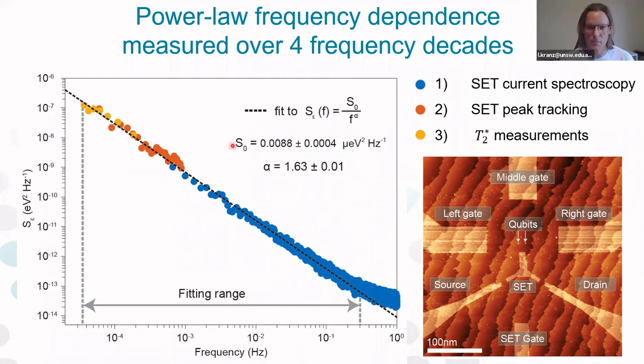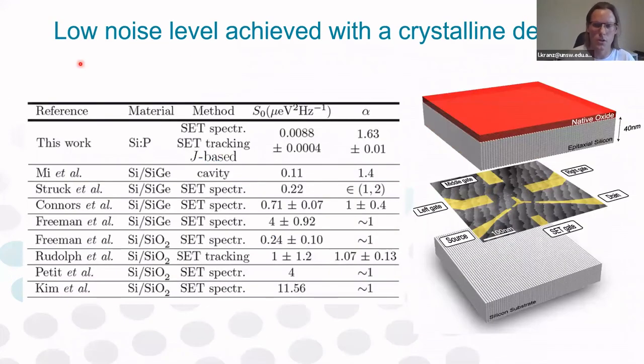Going to the second parameter that we extracted, S0, we measure 0.0088 microelectronvolts squared per hertz. Again, these are absolute energy scales, so we can compare this value to what has been previously reported. This comparison is done in this table, where we compare to previous results in quantum dots. The noise measured here is significantly smaller than what has been previously reported.